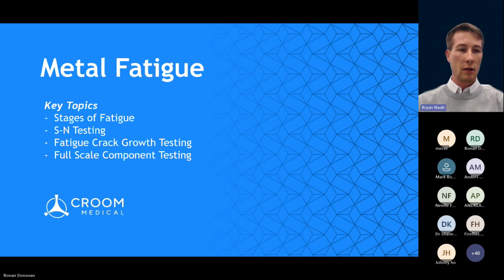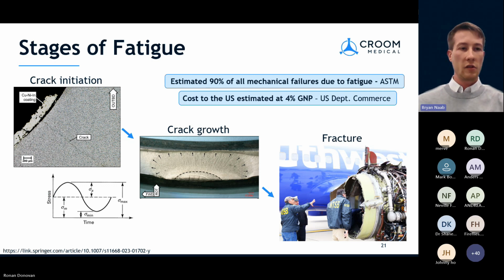I'll talk through the different stages of metal fatigue and the different methods for testing. So there are 3 stages of metal fatigue. The first stage is crack initiation. A crack can form at a defect or a microstructural feature. It's a microscopic crack at first, but as you add a number of stress cycles, that crack can grow. And that's the second stage of fatigue, crack growth. The crack can continue to grow until it reaches a critical size, where we then get fracture.